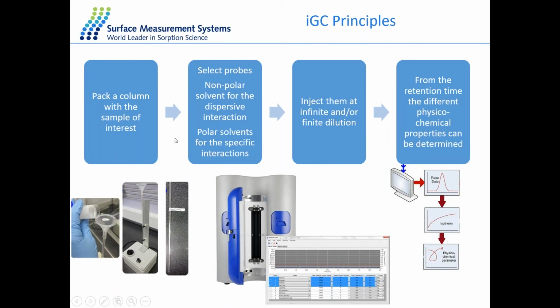So before starting an experiment, there's a few things you need to do. First is to pack a column with the sample of interest. Then go ahead and choose some probe molecules. So the most common property measured by IGC-SEA is surface energy. In this case, we need a few non-polar probes, and this gives rise to the dispersive interactions. We also need some polar probes as well, and this gives rise to specific interactions.